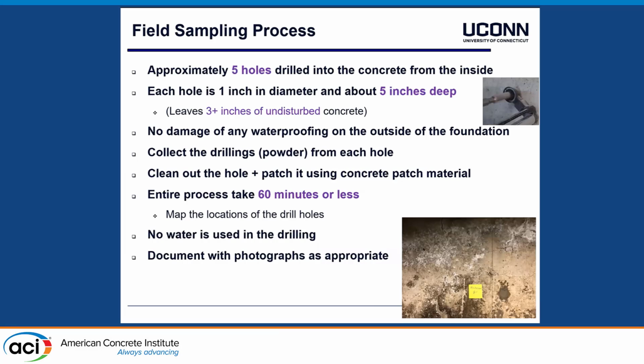We target 5 holes or drill 5 samples from each foundation. They are 1 inch in diameter, about 5 inches deep. So we leave some concrete. We don't drill through the water penetrating layer outside. We don't use any water, and about 60 minutes, and then we are done out of the homes. Again, it will be patched as you see there. So not more than 60 minutes, and then we are done there.